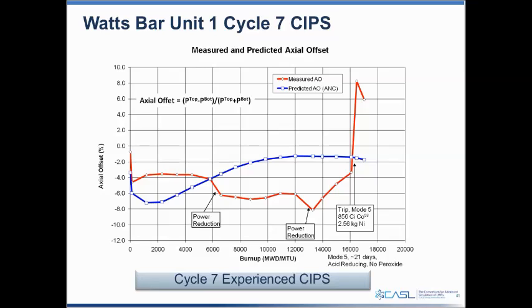You'll also see a couple of transient effects there. There was a power reduction around 6,000 megawatt days per ton. As I mentioned, what happens there is that as the power goes down, then the boron compound dissolves back out of the crud. It's been sitting in a neutron flux for a while, so it's partially depleted in boron-10, the neutron absorber.